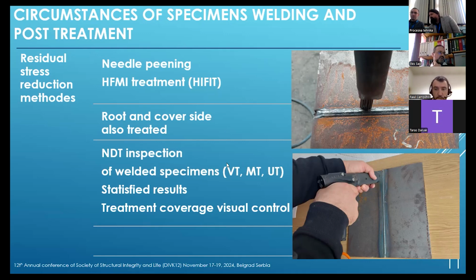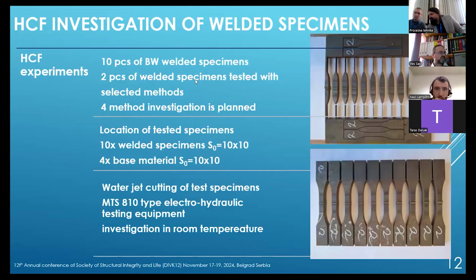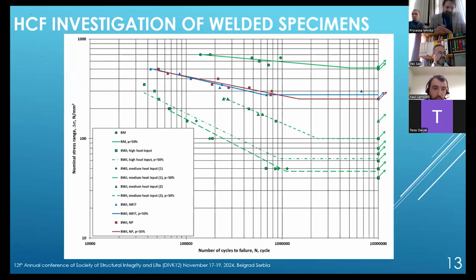After investigating these specimens by visual, magnetic, and ultrasonic testing with satisfactory results, we started to prepare the test specimens for the high cycle fatigue loads. From each welded specimen, we cut 10 pieces from the weld area and 4 specimens from the base material. The size is 10 millimeters by 10 millimeters. We apply water jet cutting to eliminate any influence of the specimen preparation methods on the fatigue strength.